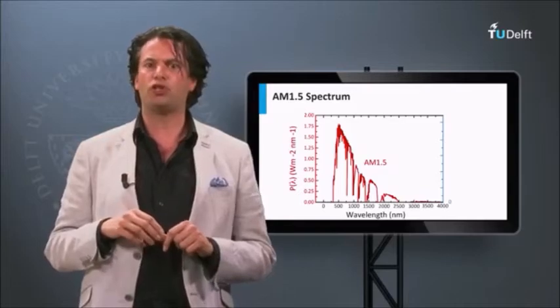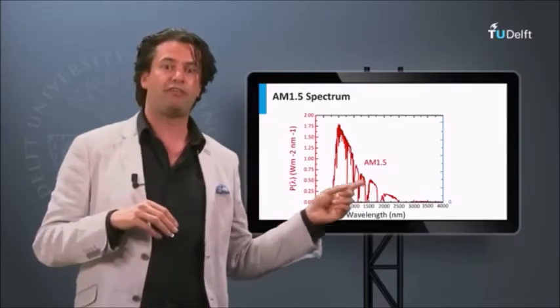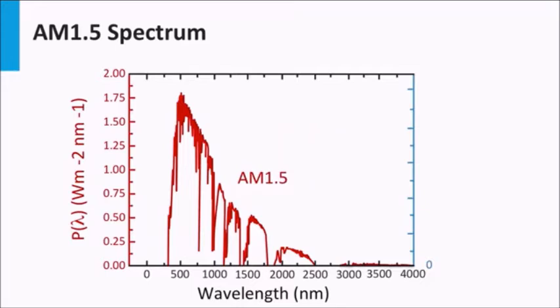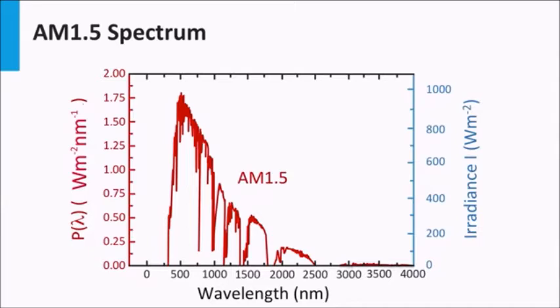As a reminder, a typical solar spectrum with the shape of air mass 1.5 is shown here. On the left vertical axis, we show the spectral power density. The irradiance in the standard test conditions has to be equal to 1000 watts per square meter and is given on the right axis. The blue line represents the irradiance and equals the area under the spectral power density up to the wavelength lambda. As illustrated, if we integrate over the entire spectral power density, the blue line, corresponding to the irradiance, equals 1000 watts per square meter. Note that 1000 watts per square meter equals 100 milliwatts per square centimeter.